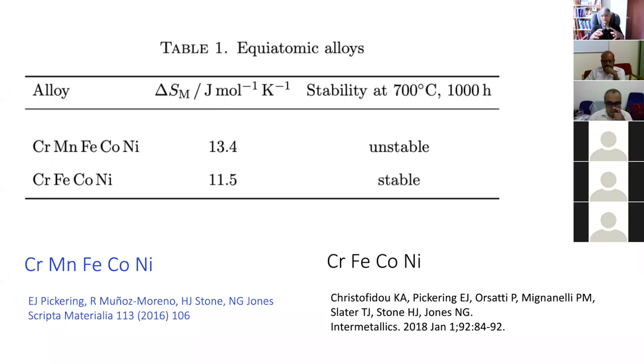So I think the entropy of mixing should be taken as a rough guide on whether you will get a solid solution, but it doesn't tell you much about stability with respect to another phase, and especially if you're going to use it at a temperature where atoms can diffuse. And generally speaking, as a rough guide, above 600 degrees centigrade, there is sufficient atomic mobility for substitutional elements, and therefore you need to think about the stability with respect to the precipitation of other phases.